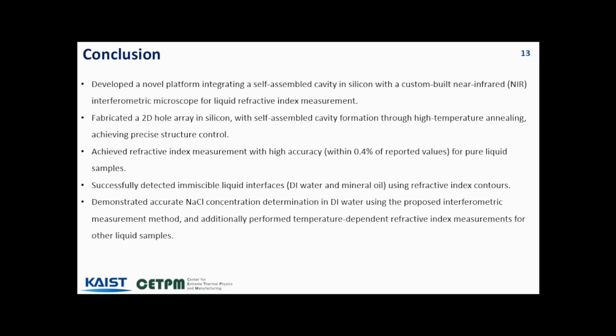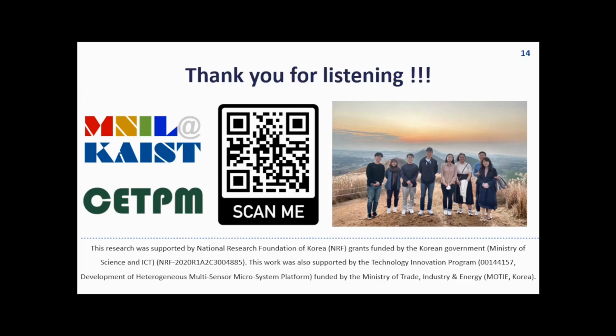Additionally, we successfully detected the interface between immiscible liquids such as DI water and mineral oil by acquiring refractive index contours. Finally, we demonstrated accurate NaCl concentration determination in DI water using our interferometric measurement method. We also performed temperature-dependent refractive index measurement for various liquid samples.